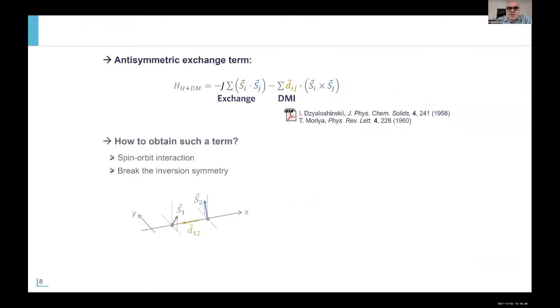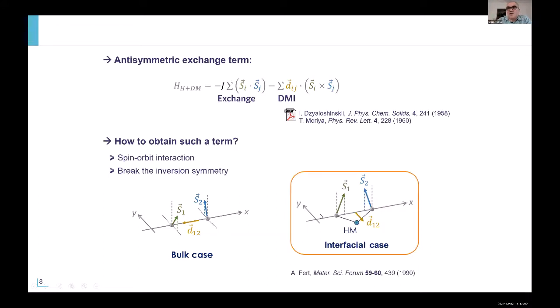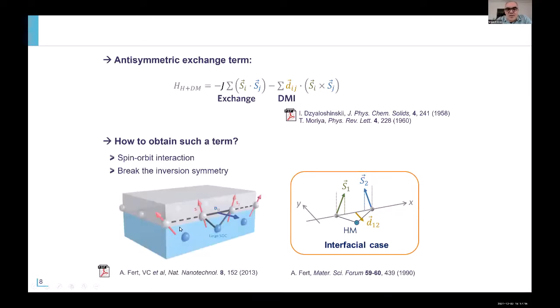So for this antisymmetric term, what are the basic principal ingredients needed to get this anisotropic exchange interaction? You do need, as I said, the spin-orbit interaction, and you need a break of the inversion symmetry. And there are different ways to obtain this break of inversion symmetry. In bulk materials, when you have a break of inversion symmetry in the crystallographic structure, you have this configuration. You see the D vector is pointing along the unit vector between S1 and S2. And in the case that we are interested in, so interfaces and thin films, the D vector, as you see, is perpendicular to the plane formed by S1 and S2. And this now famous drawing of the interfacial Dzyaloshinskii-Moriya interaction is nothing else than the one described.